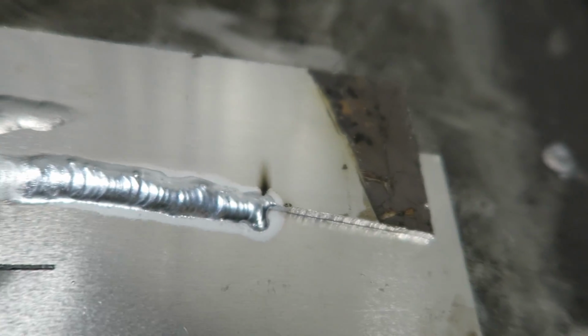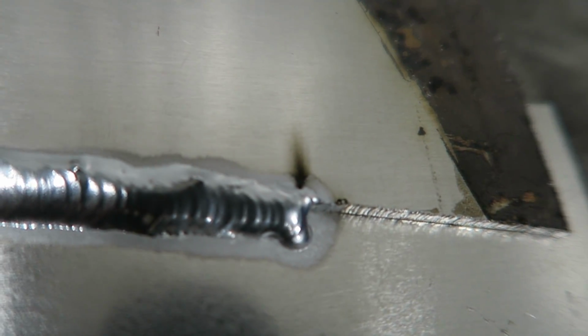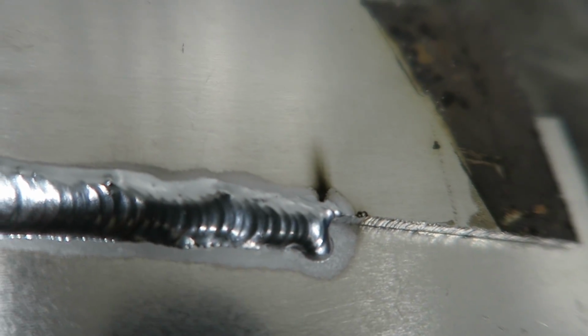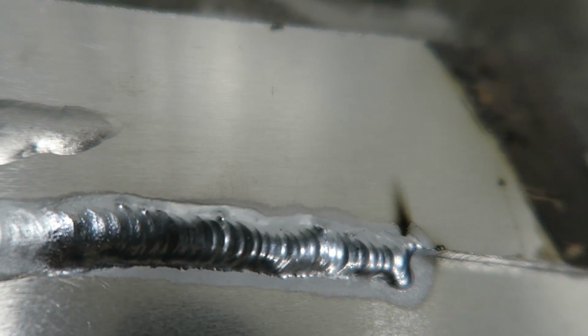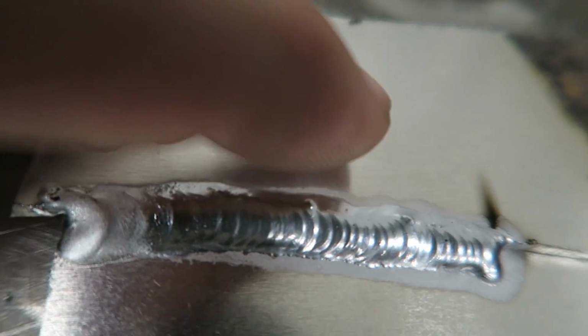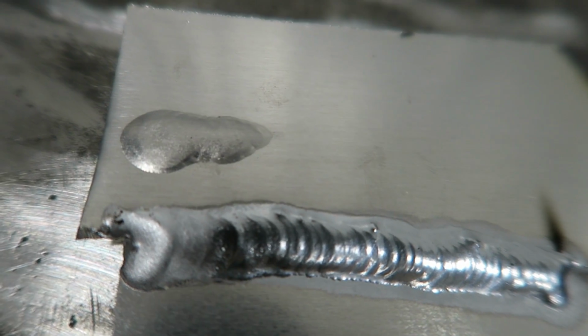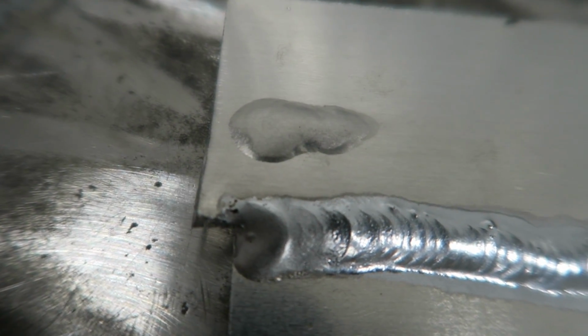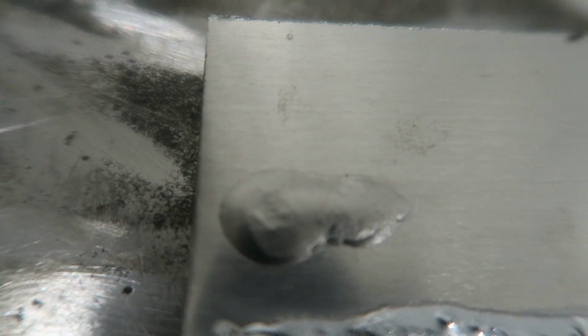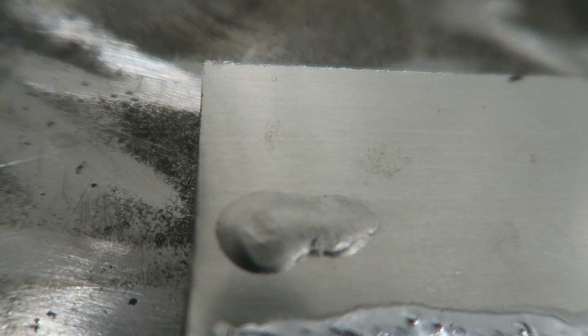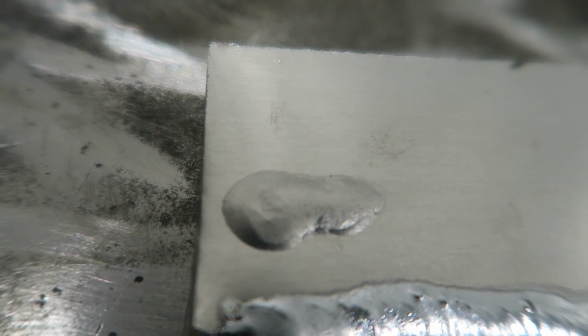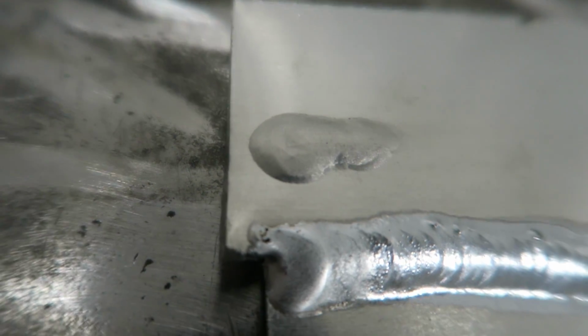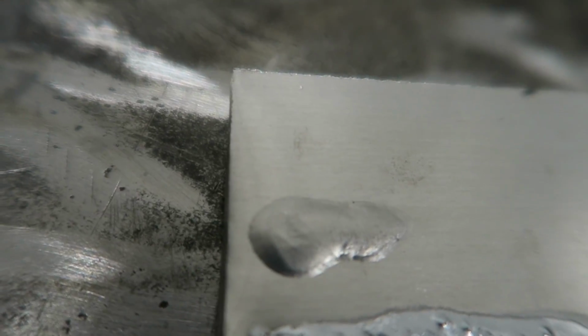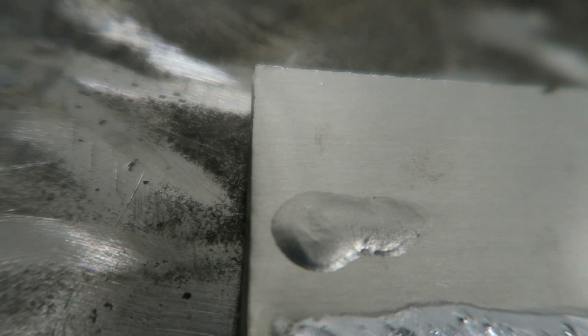So then we flipped over this piece and we did something again. We started out at a much lower amperage. We barely got it to connect the puddle there. And then we were moving, and we started to get a good pattern right in the middle here. And then I kept on the pedal at the same amperage and we washed out again. And this is what you're looking at. Now look on this side, that was the weld I just showed you on the side before with too much heat. You can actually see it penetrated through the bottom of this part, which again, not good. You want it to penetrate so that your weld is penetrated into the metal properly, but you do not want that metal falling through itself, which is what it did right there. So there's two examples of not right.